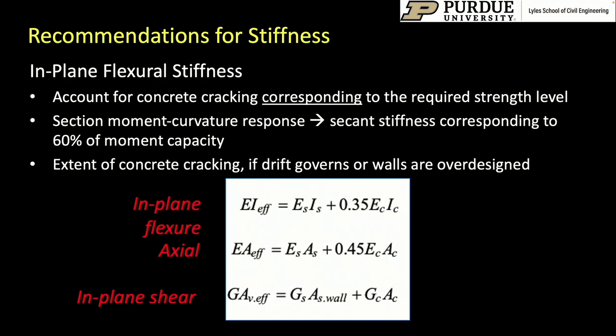So looking at the recommendations for stiffness, the stiffness recommendations should account for concrete cracking corresponding to the required strength level. We looked at the behavior of the system and we analyzed it for multiple loading conditions. And at the end of it, we looked at the section moment curvature response, particularly the secant stiffness corresponding to about 60% of the moment capacity of the cross section. And based on that, we provided some simple recommendations for modeling the system while conducting analysis to calculate the design demands. This includes the in-plane flexural recommendation, EI effective.